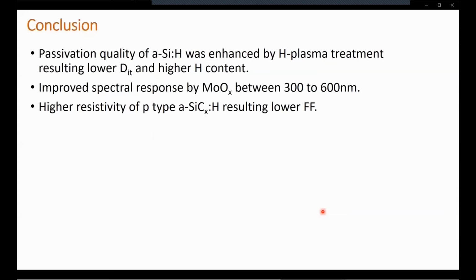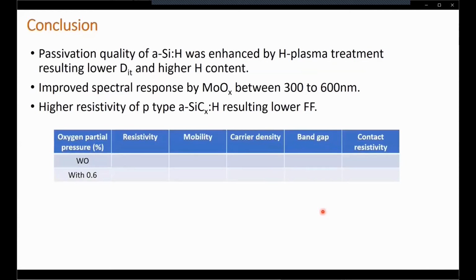For the passivation of amorphous silicon, we have enhanced the passivation quality by hydrogen plasma treatment, which is resulting in lower interface trap density and higher hydrogen content. We could improve spectral response by using molybdenum oxide between 300 and 600 nanometer. However, we have achieved higher resistivity values both for molybdenum oxide and p-type amorphous silicon carbide, which is resulting in lower fill factor. When we compare the impact of oxygen partial pressure on the electrical and optical properties, with oxygen partial pressure, resistivity and mobility values are increased, carrier density, band gap, and contact resistivity values are decreased.